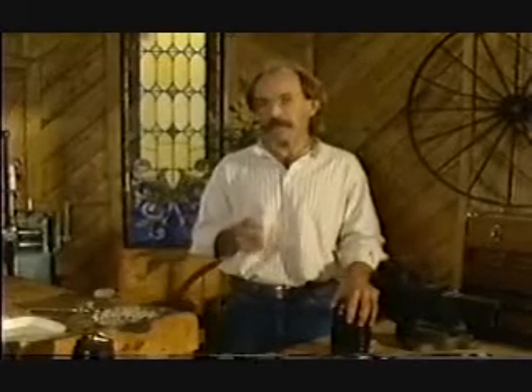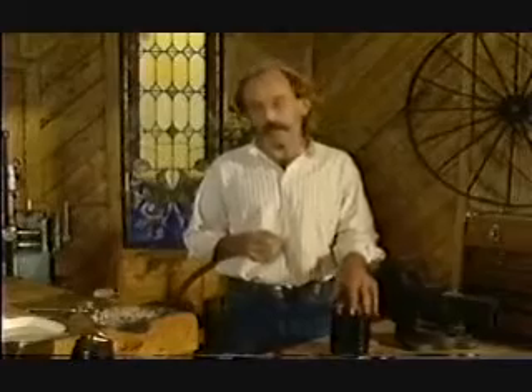Now commercially they get very complicated about this, using oils of specific viscosity heated up to a specific temperature. In our case, we don't need to be quite that critical. I'm using motor oil at room temperature. I'll be hardening just the bottom inch or so of the tool. My indicator is color. I'll be heating until it's a bright, luminous red.